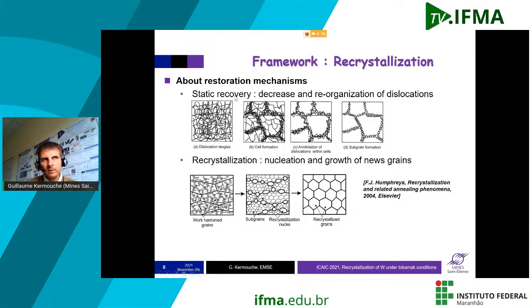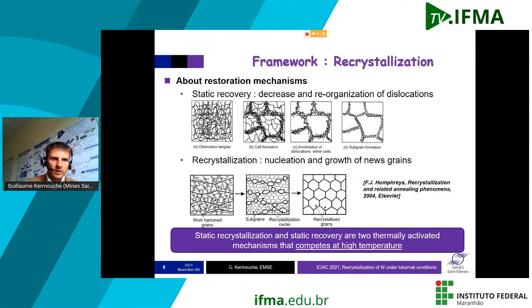The first is static recovery. The concept is to decrease the density of dislocations and reorganize with temperature the dislocations into subgrains. And the material here is clearly softer than this one. This is a quite slow mechanism to decrease the mechanical properties. And the second one is recrystallization. This is totally different because in this case, in the microstructure, there will be a new grain that nucleates, usually at the grain boundary. And this new grain will grow at the expense of the former microstructure. And this is driven by the stored energy in the material, that means the dislocation density. So these are two different mechanisms that can happen at high temperature. And they can compete.